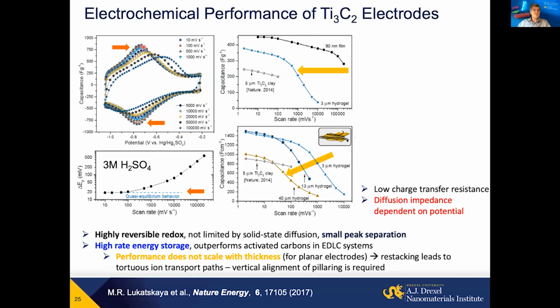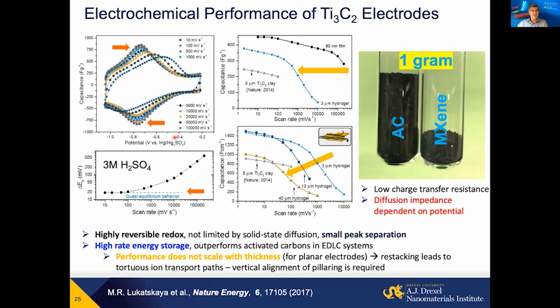For example, I'm showing here cyclic voltammograms for MXenes in sulfuric acid, basically a protic electrolyte. And what you will see, at close to 0 volt, there is a double layer type of capacitive behavior. But at lower negative potentials, there is just a wide redox peak overlaid on a double layer envelope. Moreover, this behavior, redox reaction, is possible up to rates of 100, even 200 volts per second. So what does it practically mean? It's possible to have redox energy storage at enormous rate, millisecond time, as long as you have metallically conducting, highly conducting materials, because in most cases, we're really limited not by ionic, but by electronic conductivity of our electrode materials. And this is very important fundamentally.